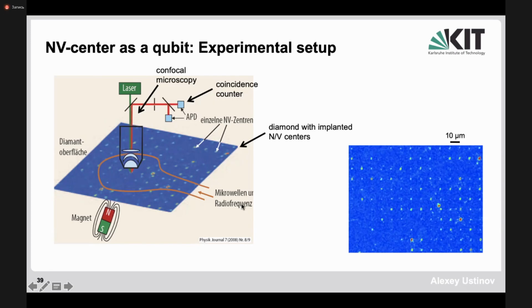On the picture on the right, you see actually the defects which were implanted using the focused nitrogen ion beam, and then annealed, and then you see here that individual defects, they show fluorescent response. You can control this, of course, by microwaves, as I said, and also by magnetic field. I should mention that pioneers of this field were 2 physicists from Stuttgart. This is Jörg Wrachtrup and Fedor Jelezko, actually scientist who is now professor in Ulm, and his background is in, actually he comes from Belarus, by his education, and has been working in Germany for many years.